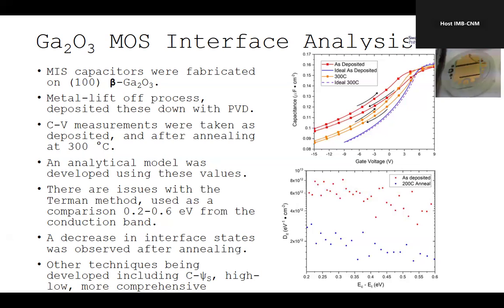Because of these failure mechanisms in silicon carbide, with a small band offset between the silicon dioxide and the silicon carbide, the failure of that interface is exacerbated at higher temperatures. And gallium oxide is going to run at higher temperature, so it's going to be even worse. There are going to be big challenges for reliability, but we're not near that yet.